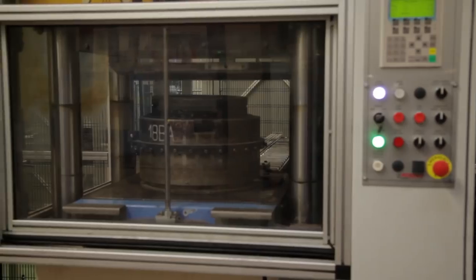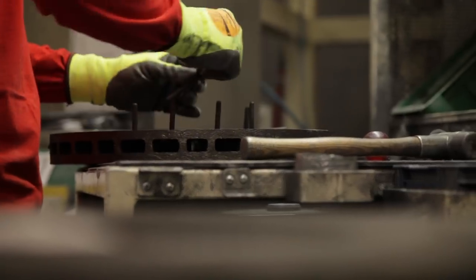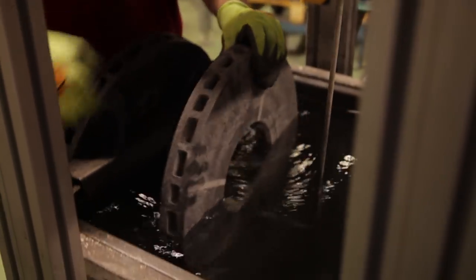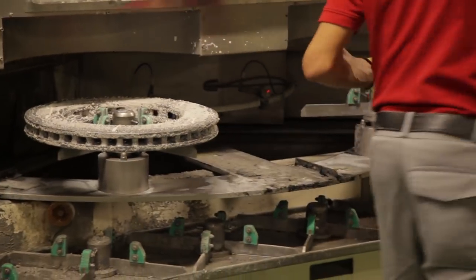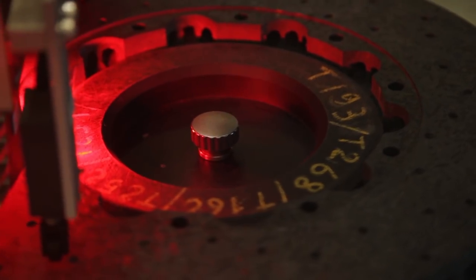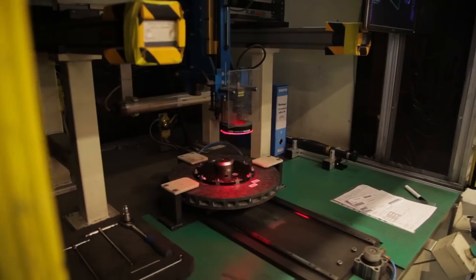The compound goes through a third thermal stage, called anti-oxidation, which serves to shield the carbon fiber during vehicle use. The final shapes and dimensions are obtained by means of mechanical processing, through the use of numerical control machines and high-resistance diamond tools, which can process the hardness of silicon carbide, from which the disks are made up of. The disks then undergo a microstructural 100% control, aimed at identifying potential surface defects, and all the components are finally assembled.